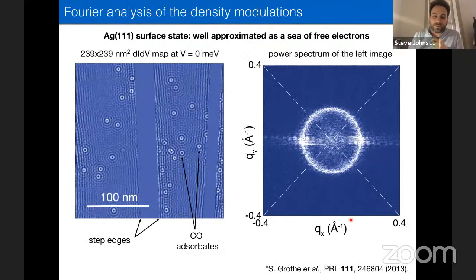To show you an example of this, I like to pull this old paper from postdoc work that I did when I was at UBC. This is a scanning tunneling microscopy image of carbon monoxide atoms on the 111 surface of silver. I like this example because it's a Shockley surface state in the 111 surface, and it's a very beautiful free-electron-like band structure, a nice parabolic band. You can describe everything almost perfectly with free electrons.